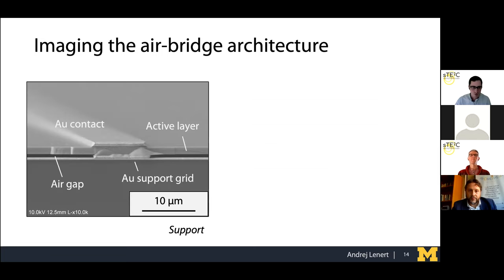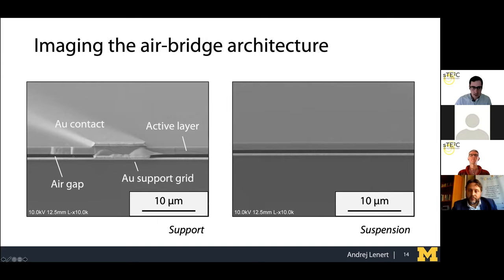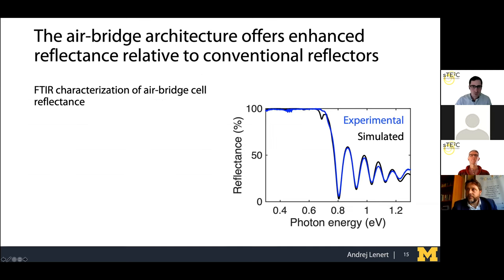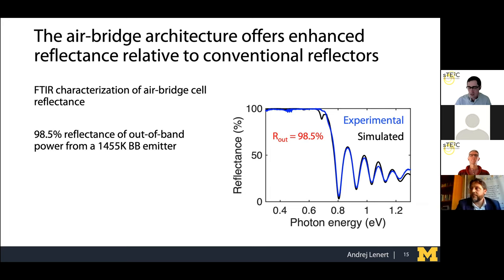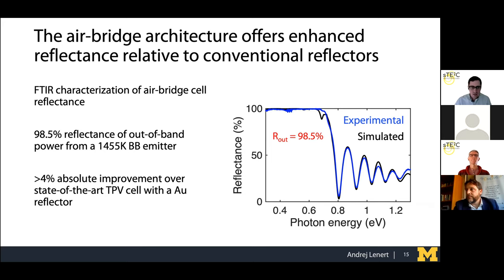So if we zoom in, we see these beautiful pictures where we have this thin 600 nanometer layer of air that's separating the absorber from the gold mirror. And we see that we have a very wide span, about 80 microns across between gold supports, that we're able to achieve. And we can sustain this very small gap of air. So now when we look experimentally and compare to our simulations, we're able to actually match our simulations. We no longer have that unexpected parasitic absorption. And so we can achieve about 98.5% out of band reflectance. And this is 4% higher than we've done before, and about 4.5%, or closer to 5%, better than the cells that were achieved by the Berkeley group.